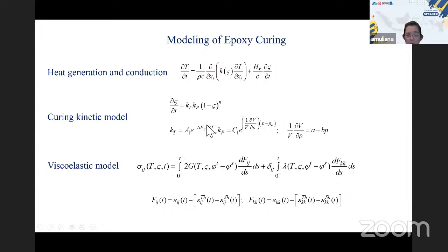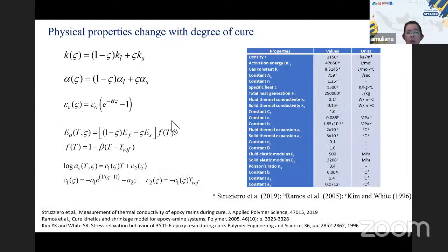Now, this curing process also depends on the temperature and the pressure, right? So when you change the pressure and temperature, it changes the curing reaction rate. By being viscoelastic, again, the property changes with the degree of curing and temperature, right? So when it's in the liquid stage, it's highly viscous. As it gets solidified, the polymer is harder, so the viscosity is actually decreasing. So all of these would affect the overall viscoelastic response of the polymer. Now we also incorporate the expansion and the shrinkage in capturing this epoxy curing. So we also account for the changes in the physical properties, right? So this is thermal conductivity, thermal expansion, and mechanical properties. And this is the shrinkage model, right? So all of this change from the liquid state to the solid state will also affect the overall curing response.